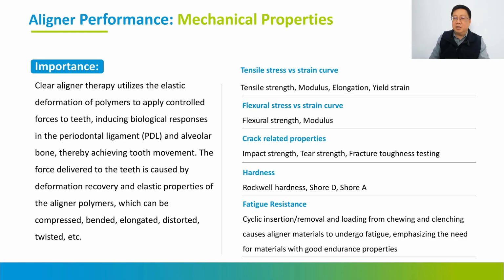The hardness, actually, is based on a scale. If we go to a very soft material, we can use Shore A, or even lower than Shore A, there is Shore 0 or Shore 00 to measure sponge. And Shore A is very normal to measure the hardness of elastomers. However, if the hardness is more than 90 Shore A, it's very difficult to tell the difference between 90 and 95. Then they will move to another scale called Shore D.